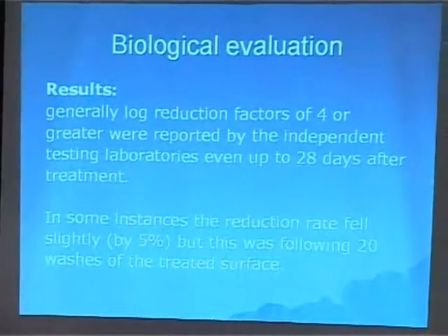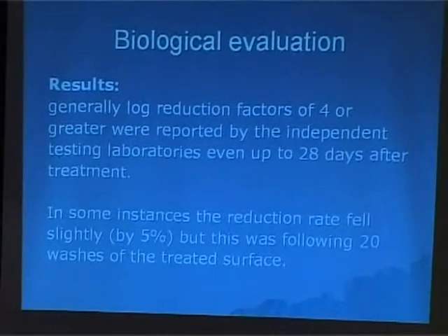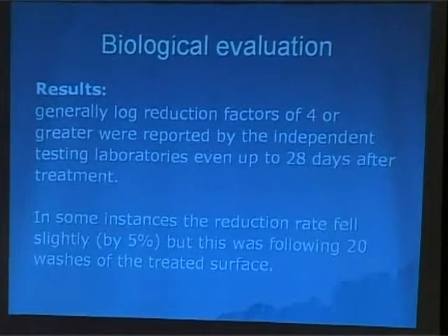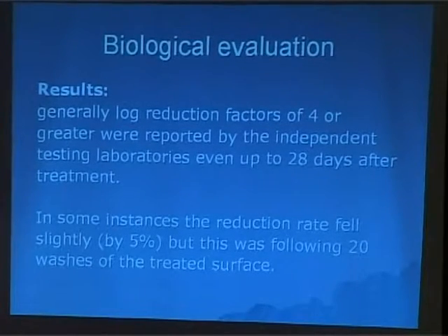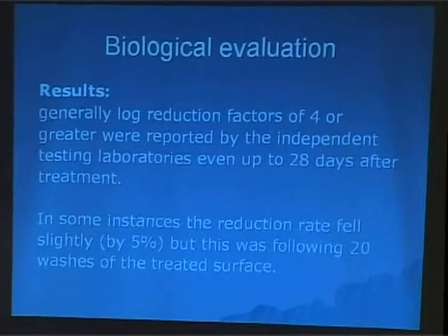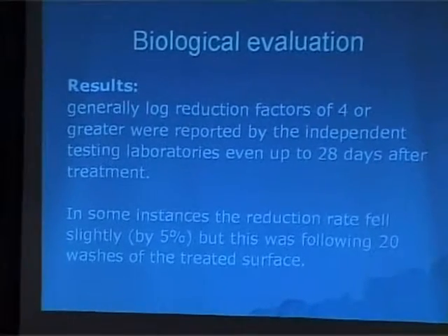What sort of results did we get when we put this on? Remember, the 24-hour contact, even at loadings as small as 0.01%. In other words, 100 parts per million of material loaded into a concrete sample. Log reduction factors greater than 4. And the important thing was that that log reduction factor was obtained after 28 days.